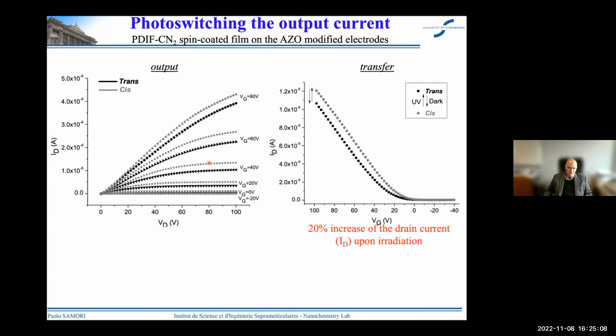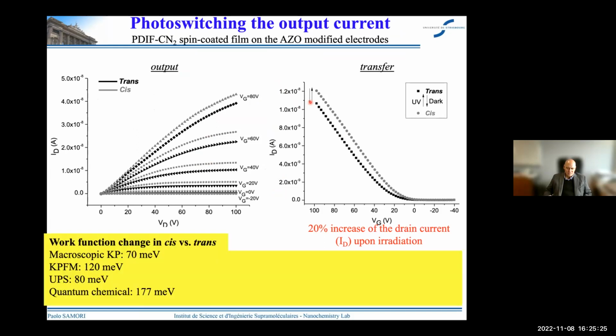This is something you can observe here, both in the output and in the transfer characteristics. When you have the azobenzene molecules in the cis form, the barrier is thinner and therefore the current is higher, since we are tunneling through a thinner layer. And actually we thought that there could be a role played by the different work function of the SAM in the two states, but different techniques that have been exploited demonstrated that the change in the work function in the two states is very, very modest. And therefore the difference in current we observe is indeed due to the fact that we are injecting charges through an insulating barrier, and we have a tunneling process that is ruled by the thickness of our barrier.